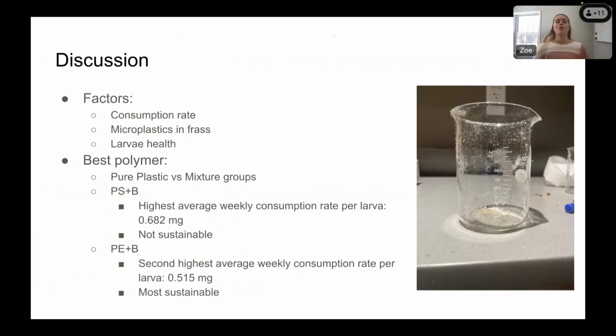So just to review, the factors I was looking at in this experiment were the consumption rate, the microplastics in the frass, and the larvae health. Overall, the mixture groups performed much better than the pure plastic groups in terms of all three of these factors. They had higher consumption rates, better health, and less microplastics in their frass, if any. The polystyrene bran had the highest consumption rate. However, it wasn't as sustainable in terms of microplastics as the polyethylene.